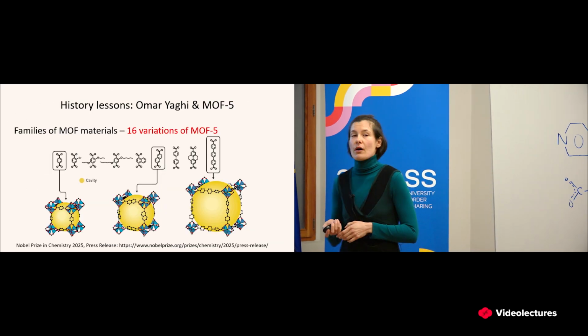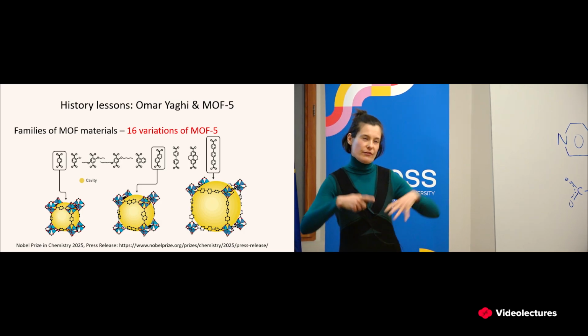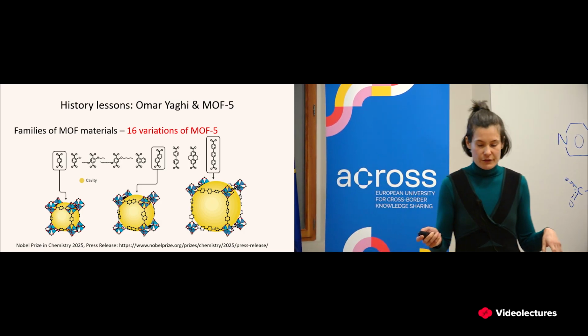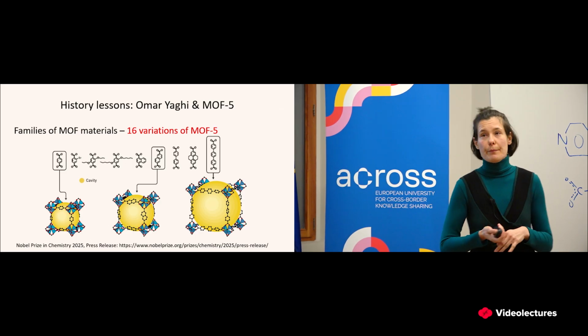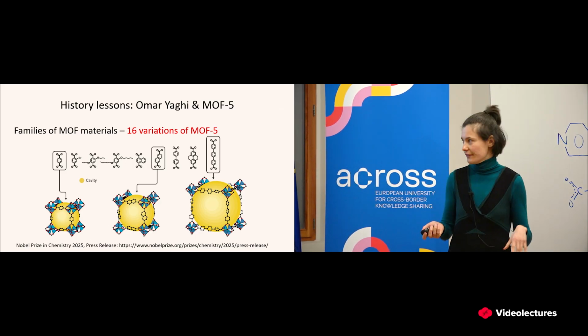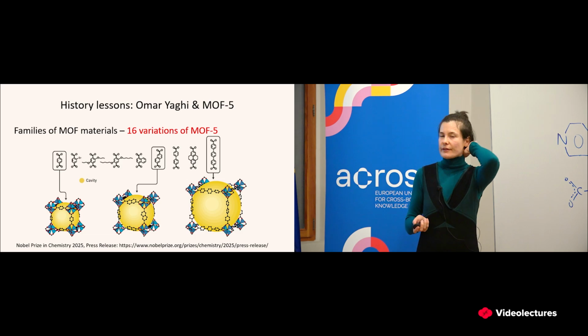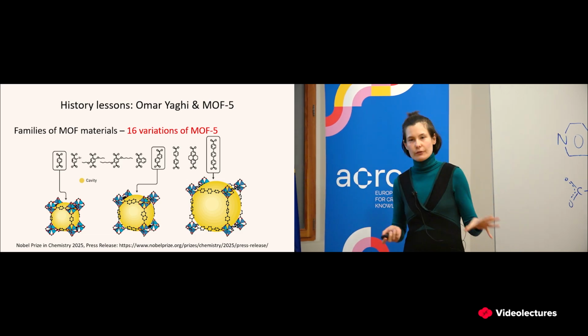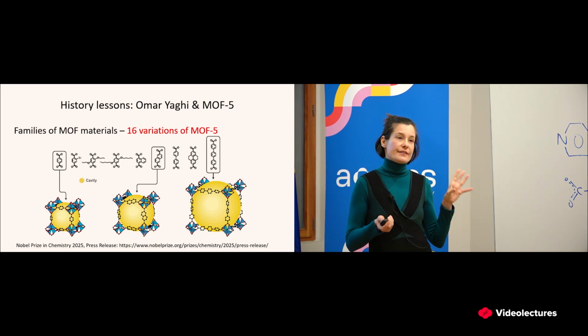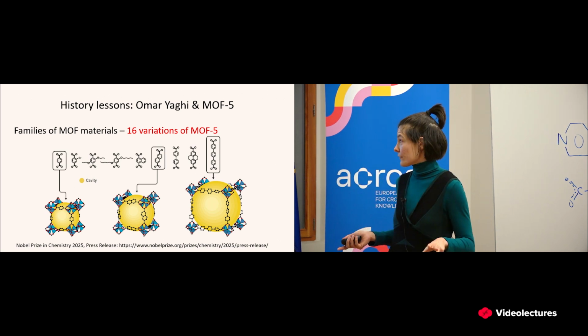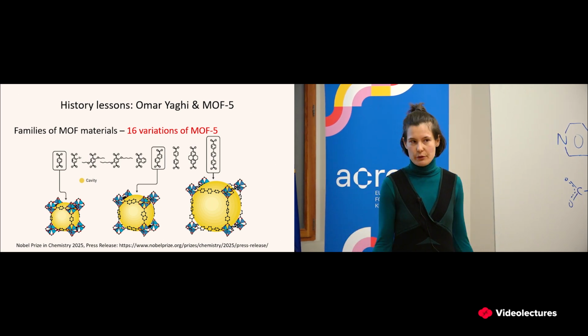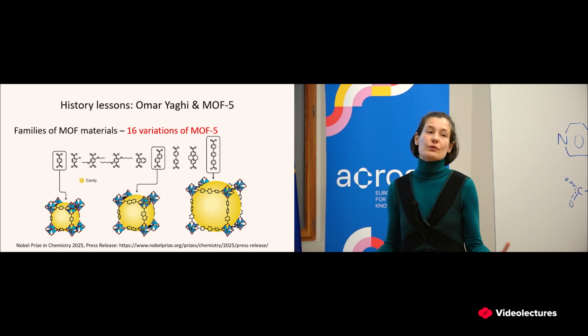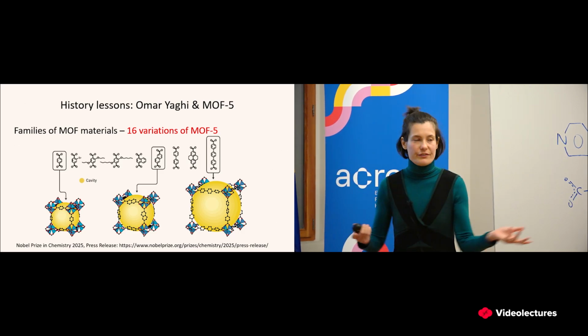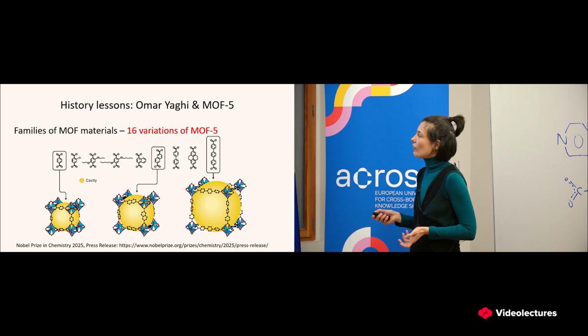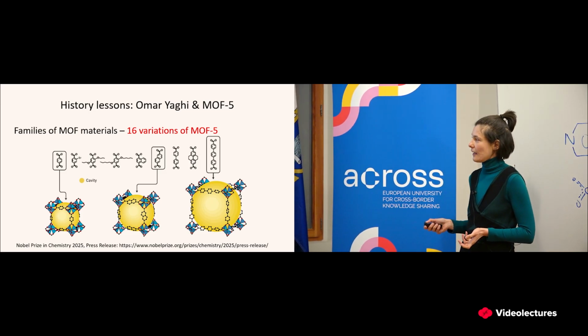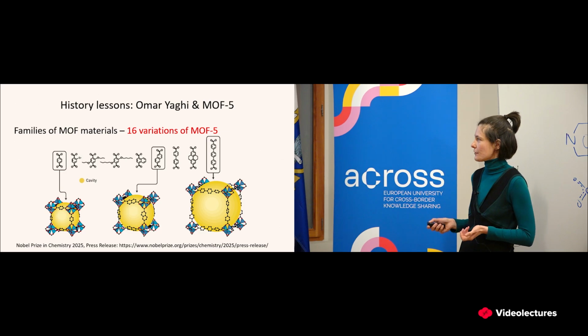But this story with MOF-5 doesn't end here. It's not just a material with a very large surface area. This is also the first time that a MOF family was created. Professor Yaghi's group showed that using the same metal cluster and structurally similar but not exactly the same linkers, they can create a family of metal organic frameworks, and they can tune the properties of these materials in a predictable way, right? So the original MOF-5 used this linker and had this shape or molecular structure.